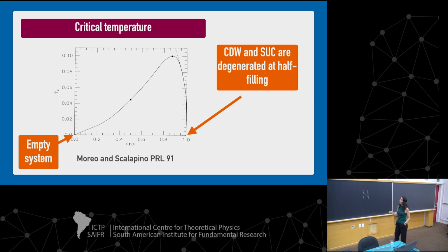This is a phase diagram obtained in the 90s for the attractive Hubbard model. And if today you try to publish a phase diagram with 2 points, I don't think you're going to get through, but in the 90s you could. And it was very, very clever because Adriana and Doug knew that for the empty system, TC has to be 0, you have no particles. And they know, because of the Mermin-Wagner theorem, at half filling, it has to be 0 because of symmetry. So they have these 2 points, and they draw the line. And I think it's so clever.